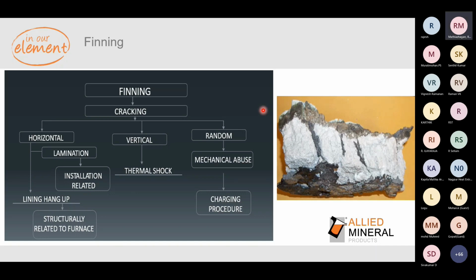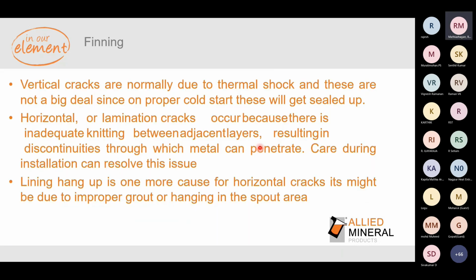Vertical cracks, which are thermal cracks, are very easy to seal up if you follow a proper cold start procedure. Random cracks are mechanical abuse. It's because of the way we charge the furnace, or any unbalance in your hydraulics or your structural things. Otherwise random cracks will not happen. And random cracks, again, are very hard to seal up, and they can also lead to metal penetration issues. So as I said earlier.